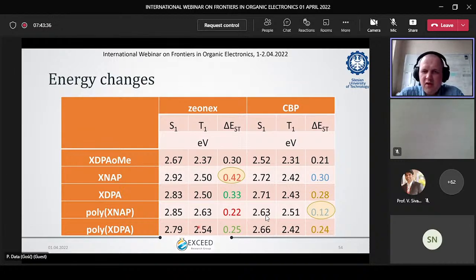So like here in the table, if we compare our small molecules, so the monomer and the polymer, we drop our ST gap 4 times, and that's quite significant by simple electrochemical modification. What is also interesting here is that we affect a little bit more of our triplet state. Our triplet state rises a little bit. It shouldn't, but it seems so that it rises because the XNAP molecule had naphthalene here, and what we found out is that naphthalene works here as a steric hindrance and pushes the acceptor a little bit from the plane.